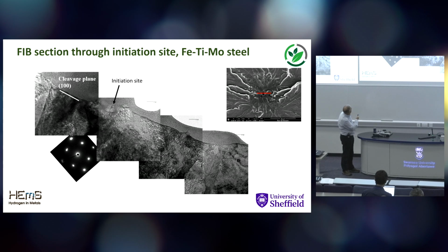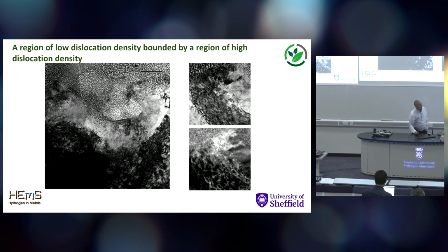You see immediately propagation is predominantly on the 100 cleavage planes, but what we're interested in is what was going on at the initiation to see whether we could see it. It looks a complete mess, very different structure to what we've seen before. So here's that hole that you could see in the SEM.